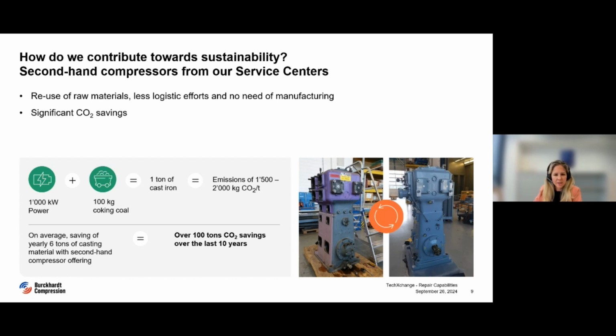On average, about 1,000 kilowatt hours of electricity and 100 kilos of coking coal are required to produce 1 ton of cast iron. The use of which is associated with corresponding emissions of between 1,500 and 2,000 kilos of CO2 per ton of good cast iron.